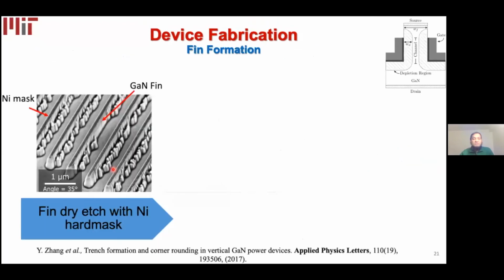The first most important step in our fabrication technology is the fin formation. For the fin formation, we deposit a silicon nickel hard mask through e-beam lithography and e-beam evaporation and do a dry etch to define the fin length and width. And after the dry etch, as we can see from this SEM image, there is a lot of sidewall damage from the dry etch.